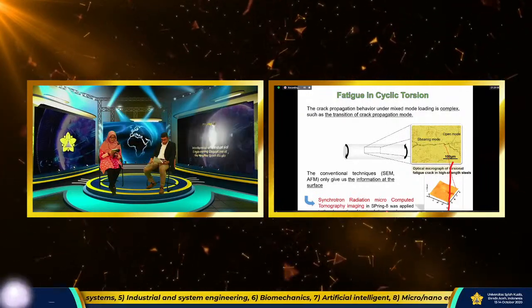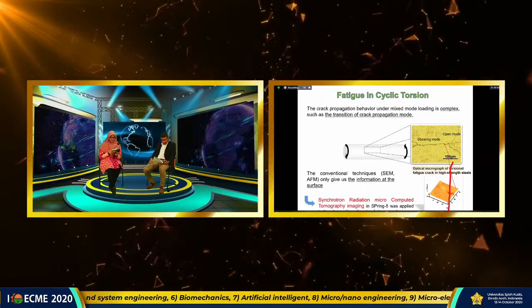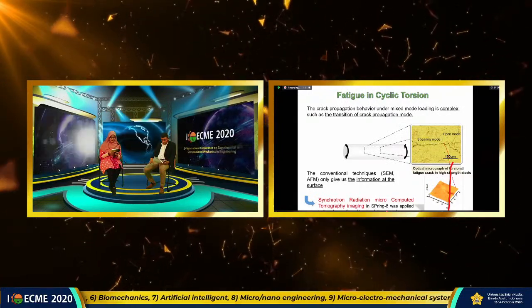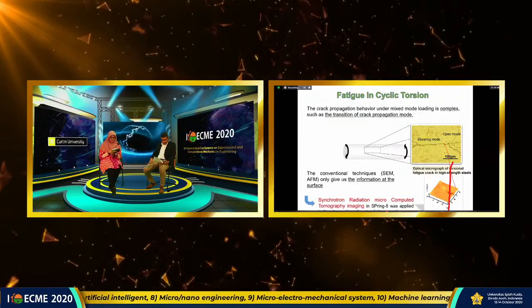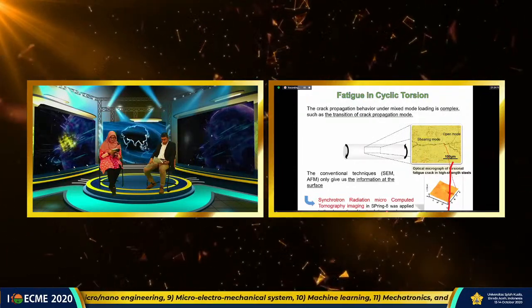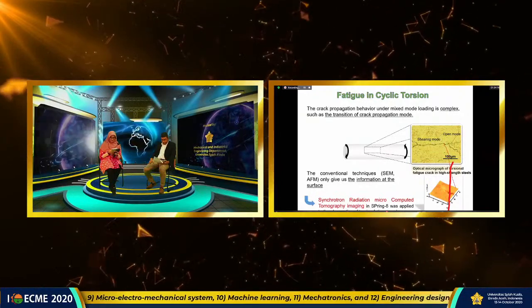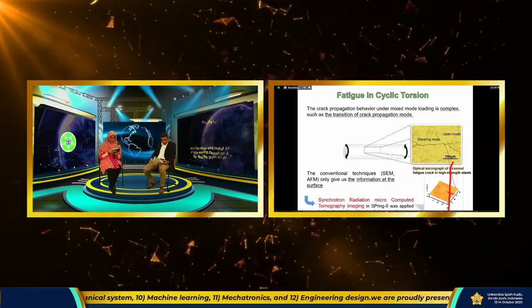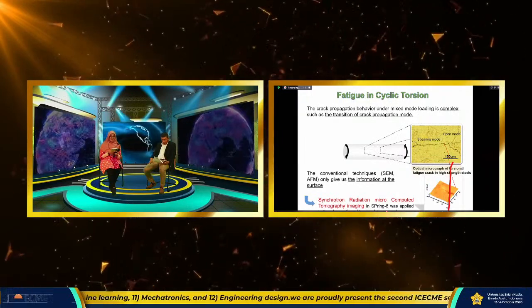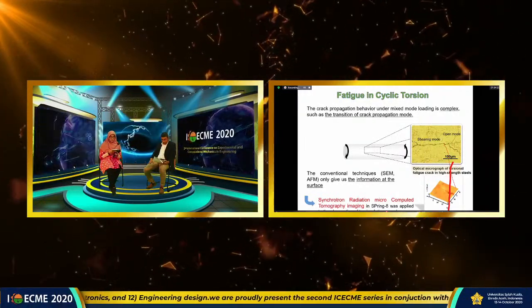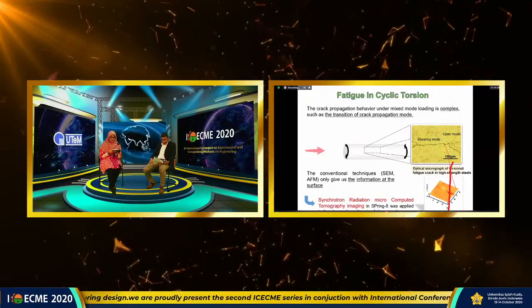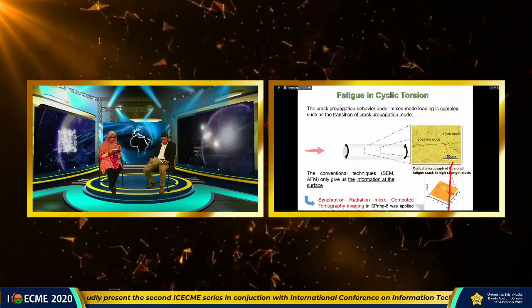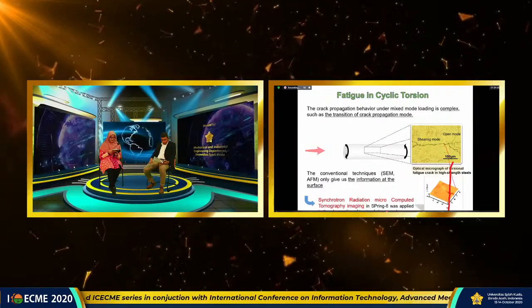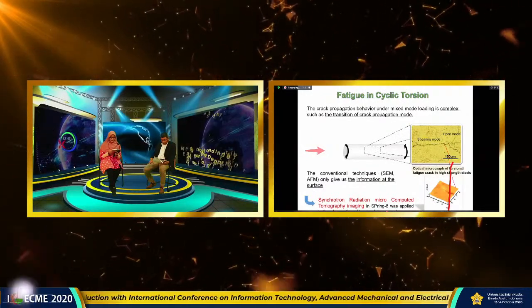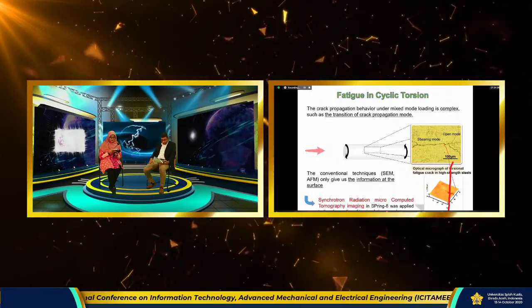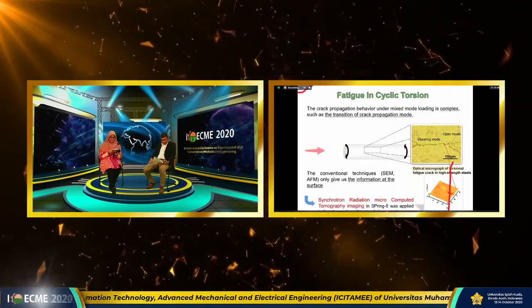Fatigue crack initiated under cyclic torsion is one example of this mixed mode. The crack propagation under torsion is usually studied through observation at the surface, and it is difficult to understand the crack behavior by conventional microscopies because they give us information only at the surface. Therefore, the mechanism of crack propagation under cyclic torsion could not be discussed in detail.